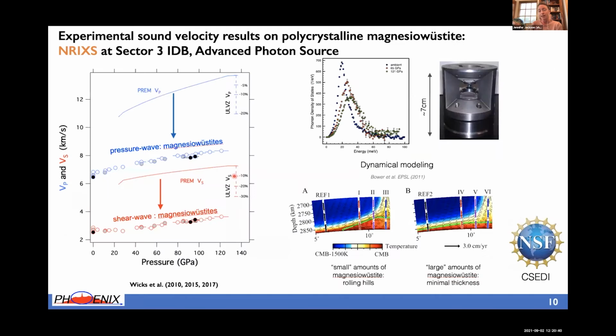And so experiments that were done initially to test this hypothesis were done by June Wicks through her PhD thesis at Caltech, working together with Dan Bower, who's a geodynamicist. Using polycrystalline data and the NRIXS method, they showed that the shear waves, and also the P waves determined through equation of state measurements, are significantly depressed with respect to PREM. So we see here the pressure wave is significantly slower compared to the 1D Earth model, and the shear wave is also significantly slower than the 1D Earth model. Combined with geodynamic simulations, a lot of the observations that had been made in the past could fit; in particular, the height and the topography could be explained by the presence of magnesiowüstite. But how much? And can we get more quantitative about this?